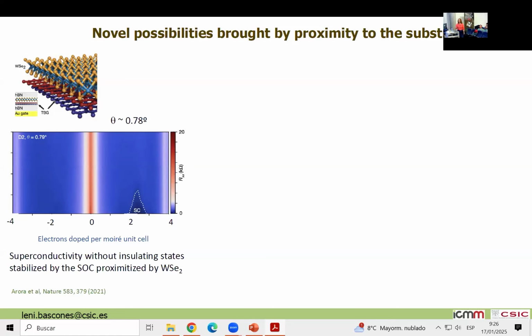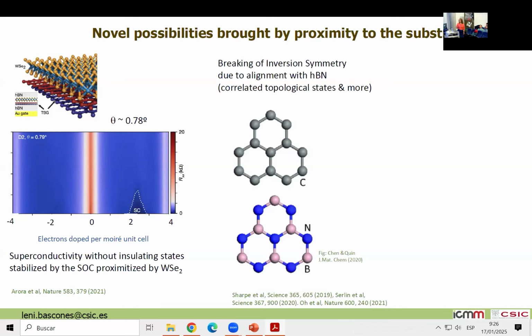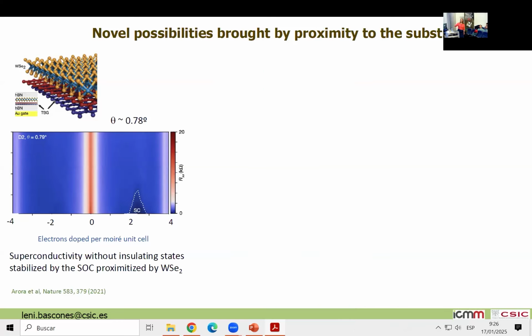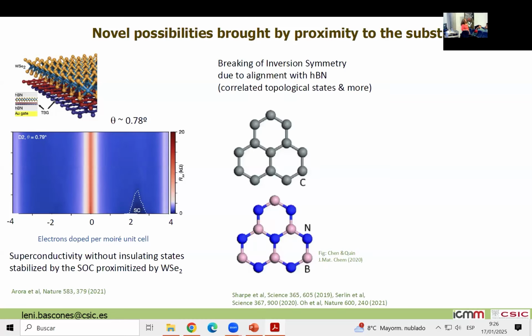And so, for example, here in this experiment, what they did was they put tungsten diselenide. Tungsten diselenide has a strong spin orbit coupling. So what they observed is that they could find superconductivity at some angles at which, without this tungsten diselenide, it was not observed. So somehow this is giving new ways.